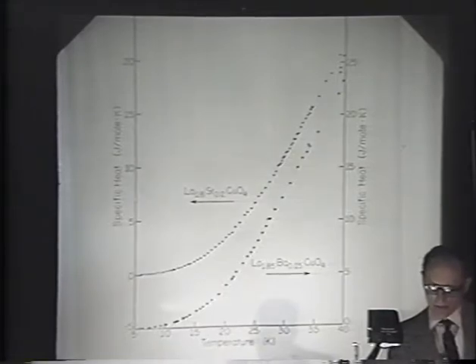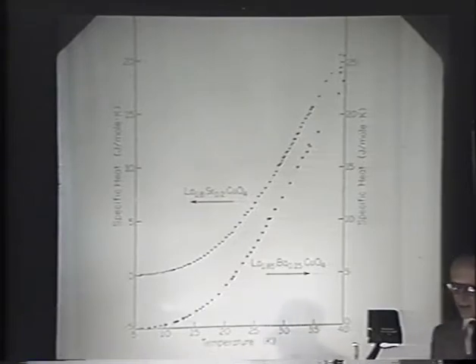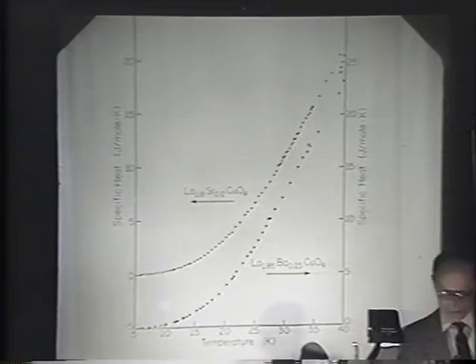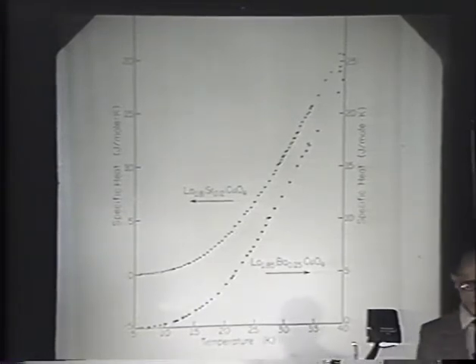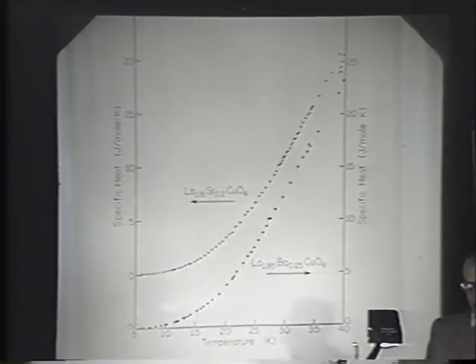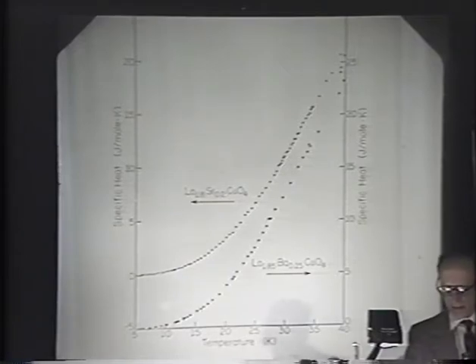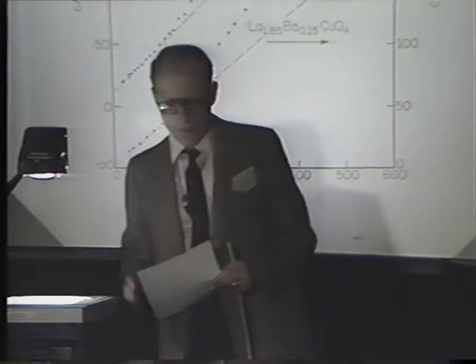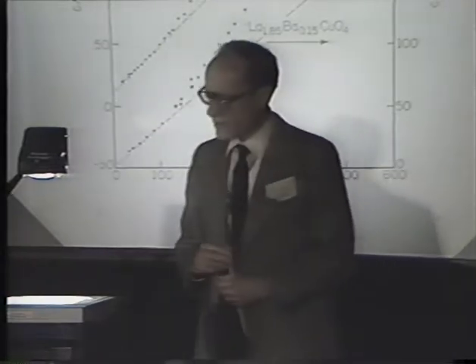The left-hand axis shows you the specific heat of the lanthanum strontium copper oxide. The right-hand axis shows you the specific heat of the lanthanum barium copper oxide as a function of temperature from 5 degrees on up to about 40. Now, what we did with these data was to plot them as C over T as a function of T squared. We did not yet measure the specific heat in a magnetic field, but I hope to show you that we've got some very interesting conclusions from the data.